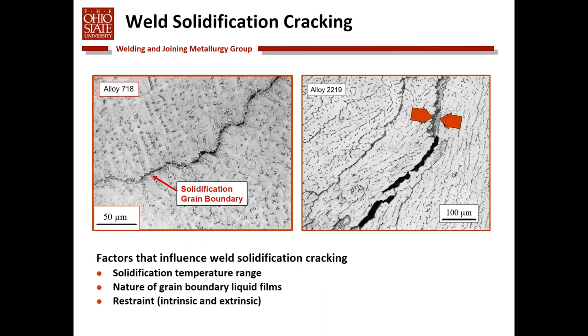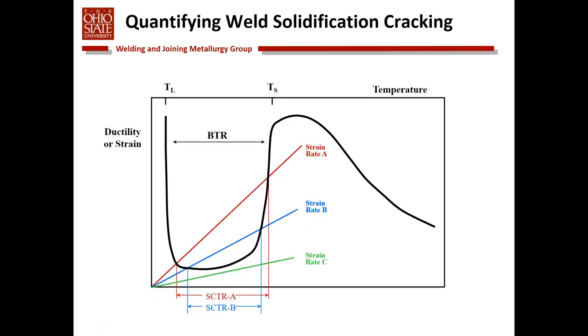Here are a couple examples of weld solidification cracking. A solidification along solidification grain boundaries. Alloy 718 is a nickel-based superalloy, contains niobium, is known to be susceptible to solidification cracking. Alloy 2219 is an aluminum copper alloy. We see solidification grain boundaries here where we get solidification cracks. And so again, these are typical examples of solidification cracking that can occur in structural materials.